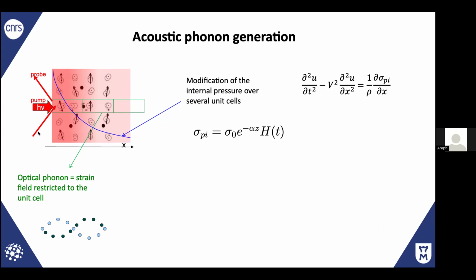Yeah, exactly. Behind that sigma zero term, there are different kinds of mechanisms you can find. There can be heating, there is deformation, but this is exactly what I will explain. So over quite a large range of wave vector and frequency, the wave equation works quite well. This does not work if you are on the edge of the Brillouin zone. But even up to the terahertz, the wave equation works pretty well for describing the lattice dynamics of coherent acoustic phonons. This is a classical equation, this is just the quantum one. Here it's the interaction: how we can convert light into mechanical energy, into a pressure. This is what I'm going to explain.